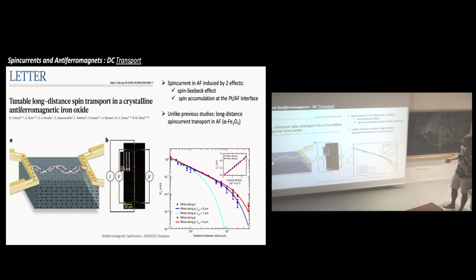So what's happening if you drive a charge current here, you will have a spin accumulation at the interface, and then you will trigger by spin torque some dynamics in the antiferromagnet. This is one effect, and the other effect is that you will heat up. And by heating up, you have thermal magnons, and this time you will have a magnetic spin current through to the detector. But the nice thing about this study is they managed to measure spin current over very long distances, microns, tens of microns. So now it's becoming very interesting, because you can think of carrying the spin information via antiferromagnetic material over very long distances. So that was quite a breakthrough.